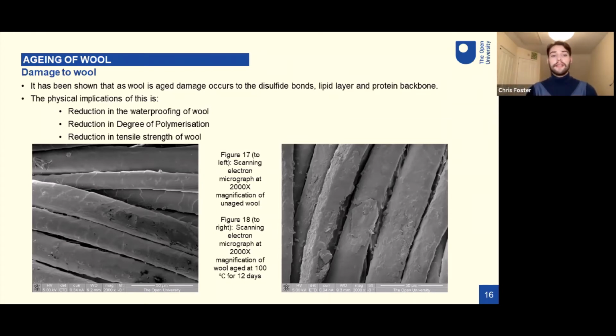You can also see a reduction in the degree of polymerization, which, if you remember, is the length of the chains of the polymers. So the actual polymer itself is being damaged. And then this ties in with the last physical implication, which is the reduction in the tensile strength. So the wool will actually become weaker with aging. Below, you can see some electron micrographs. Electron microscopy is similar to standard optical microscopy, which you may be more familiar with, except it uses electrons rather than light to image the textiles. And this is used because you can get to a much higher magnification and much higher detail.